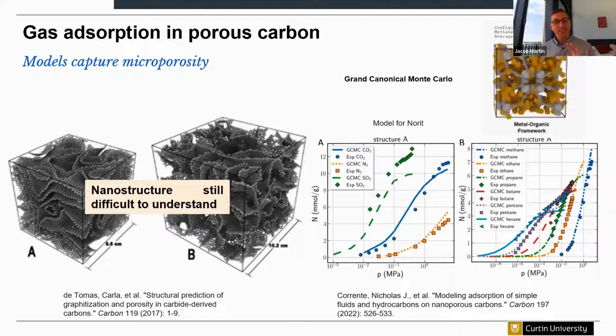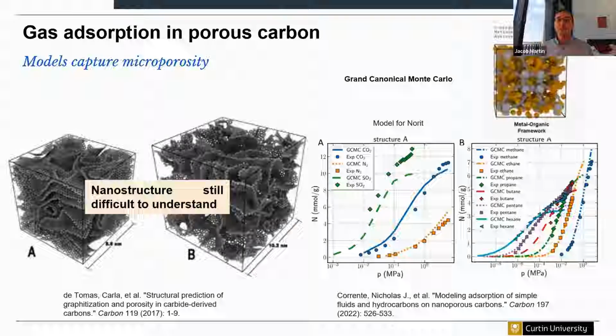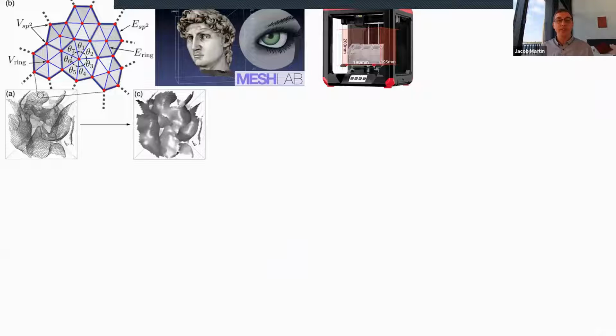But the challenge really is that even though we've got the position of every atom within this, and it seems to match all the experiments, embarrassingly, we really struggle to understand these structures. So, you know, we struggle to understand how the atoms were all connected because it was such a complex structure. I mean, we were definitely a step closer because we produced a model that at least closely analogued the physical system, but it was still too complicated a structure to understand. So we need to tease that apart, and that's where I started to look into some advanced visualization.